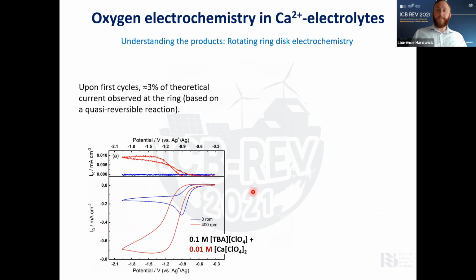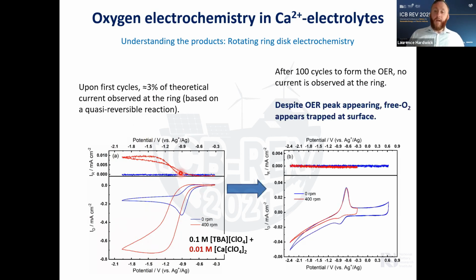So we did some rotating disc electrode experiments to try to understand, because the superoxide goes into solution, where this is ending up. In the initial cycles, we get this irreversible process, and when we have the rotating disc electrode on, at the ring side we're able to collect and oxidize some of this superoxide that's produced. So it indicates that our superoxide initially is going into solution. After a number of cycles, we now have a well-developed calcium oxide interlayer. And so we now get this reversible process.